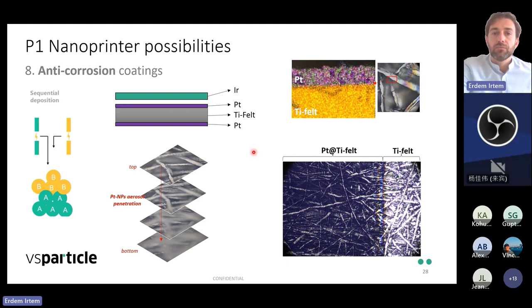immobilize platinum layers. And what we have seen, when we look from the top to the bottom, is a deep platinum penetration, which is quite different from a line-of-sight deposition system such as magnetron sputtering, which usually doesn't really deposit to the backside of the fiber, so you cannot really coat the fiber three-dimensionally. In this case, with a top-down approach, you can always, of course, flip the sample and do it again from the other side. But from analysis so far, this nanoparticle aerosol is a three-dimensional stream that is able to deposit on the entire surface.